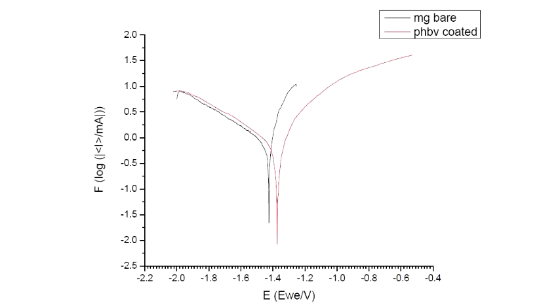Next, coming to the corrosion test, the potentiodynamic polarization curve of both the bare metal as well as the coated and treated metal has been taken, and the coated and treated metal has shown a shift in the voltage level, which signifies that the corrosion of the coated and treated metal is far lower. The corrosion rate or degradation rate is very negligible or very low when compared to that of the bare metal.